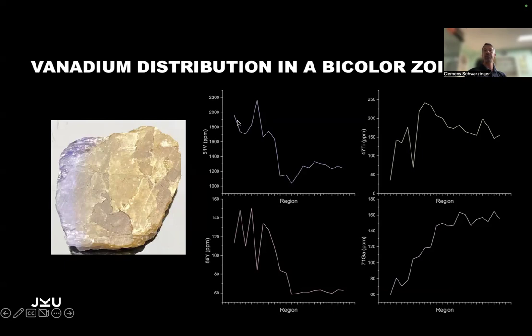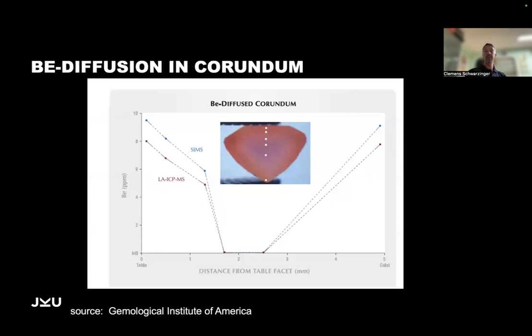Vanadium, for example, is extremely high on the outer side where we have the blue color, and then goes down where we have the yellowish brown. On the other side, you have gallium increasing towards the center, and especially titanium, you see an increase. So the yellow is somehow correlated to the titanium, whereas the blue is known to be due to the vanadium. So these are the simple things that you can do.